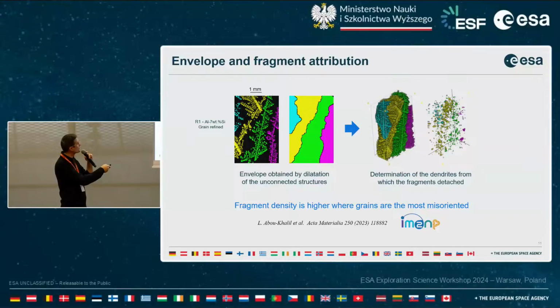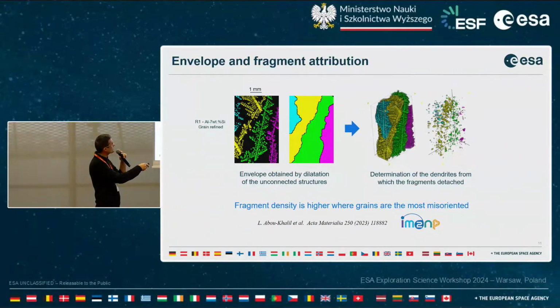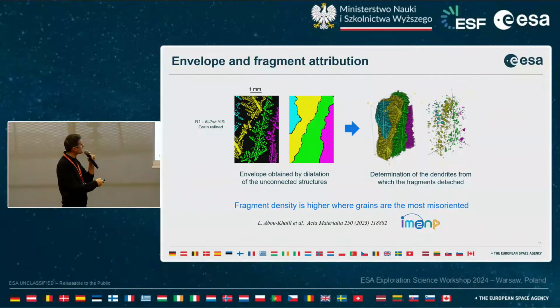to determine the structures that were connected with each other, deduce an envelope of these grains, and compare the position of the dendrites and the position of the fragments that were very tiny parts that were not connected to the dendrites. And it was possible also to determine the dendrites from which the fragments detached, and highlight the fact that the fragment density was higher where grains are the most misoriented, which illustrates actually the impact of grain competition on the fragmentation phenomena. So once again, more details can be found in this paper if you have questions, of course.